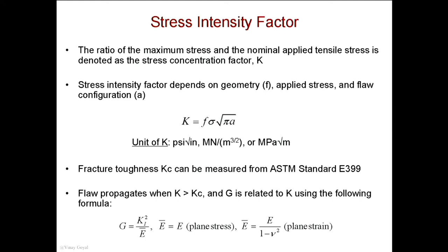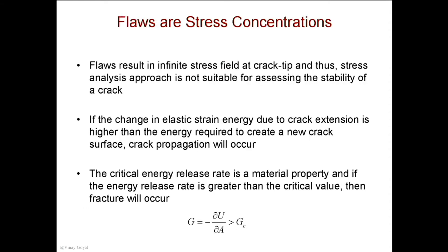Step one: run the ASTM E399 test to get the fracture toughness of the material. Then square the fracture toughness and divide by the modulus — adjusted for plane stress or plane strain accordingly — and that gives you the critical energy release rate Gc. Once you have Gc, you can compare it to G calculated from your finite element model.